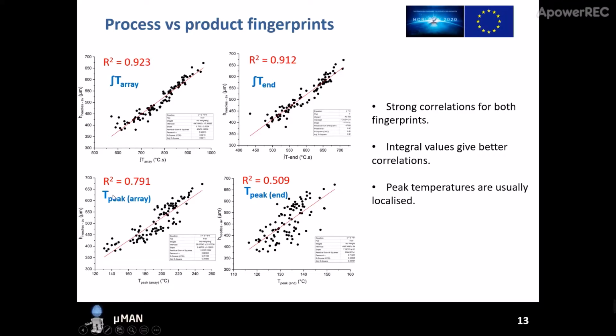Less so for peak temperatures, but there is still a strong correlation between the peak temperatures from the 6x6 array and towards the end of the cavity. The reason for this is that peak temperatures are usually one specific temperature from one specific point from the regions of interest, and they are usually localized, and they don't represent the part quality as well as the integral values. And integral values are directly proportional to the energy input to the system and viscosity of the material, so that we have very good correlations for integral values, as you can see here.